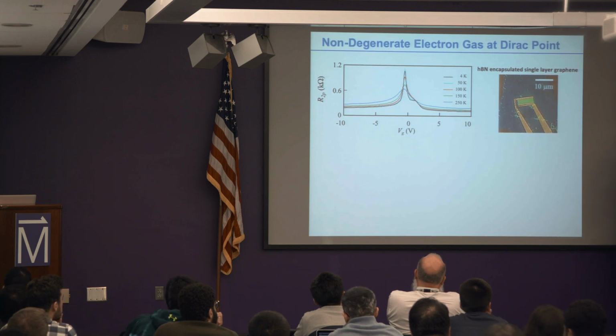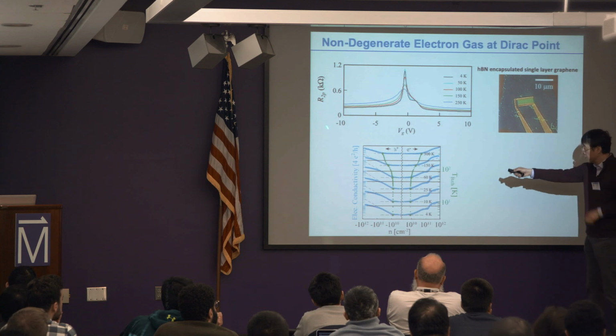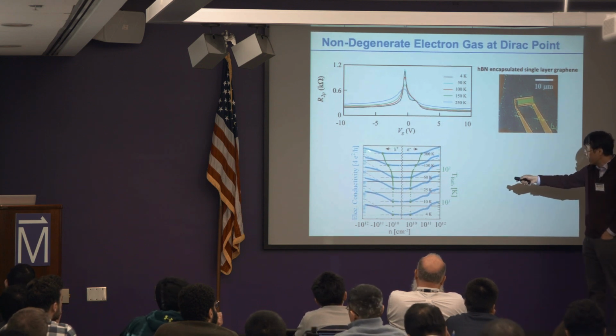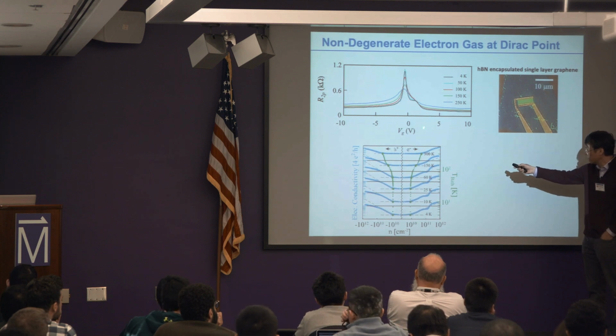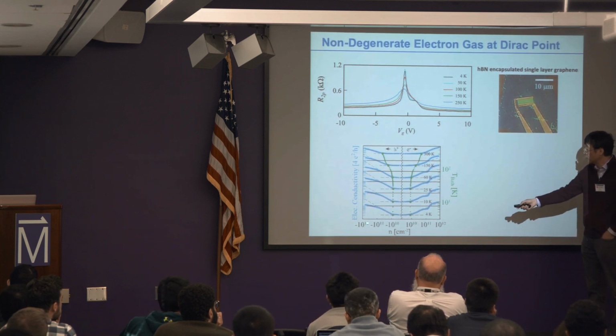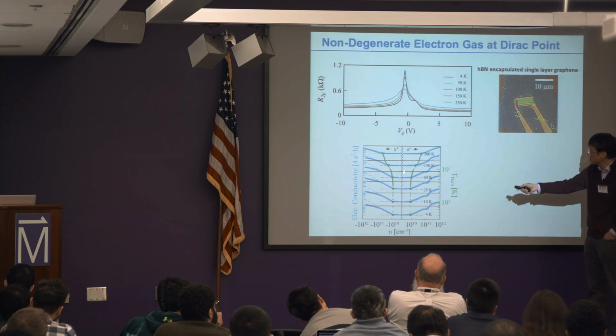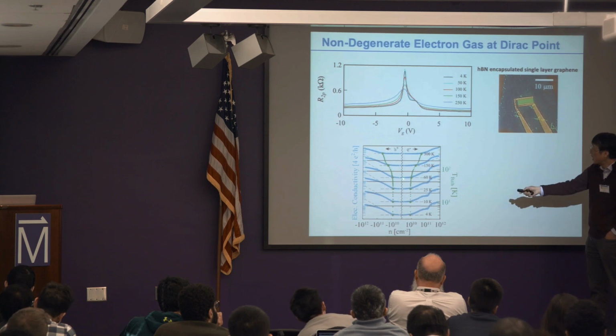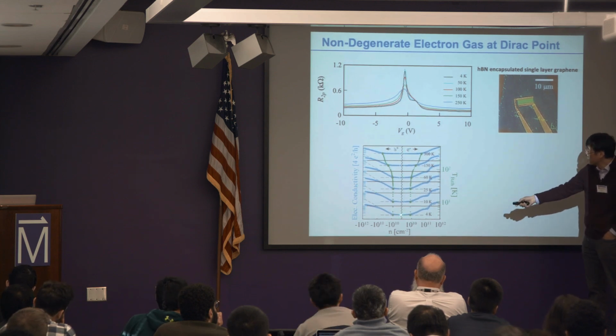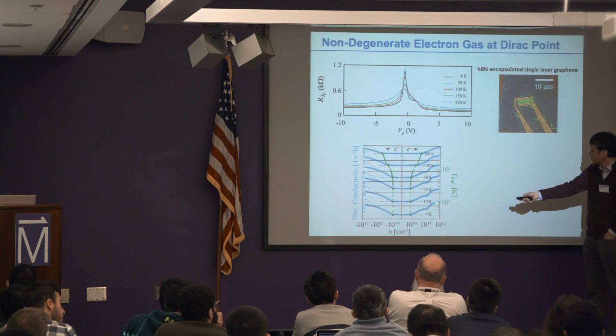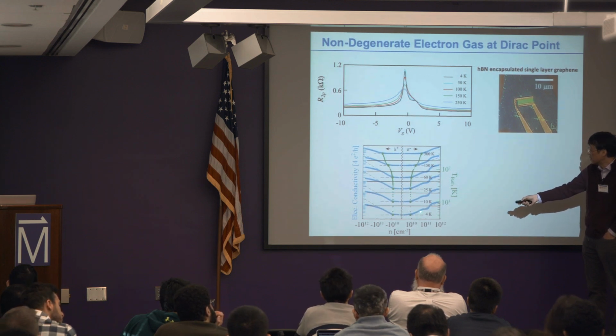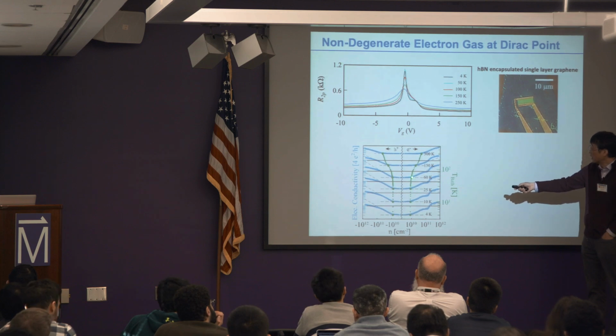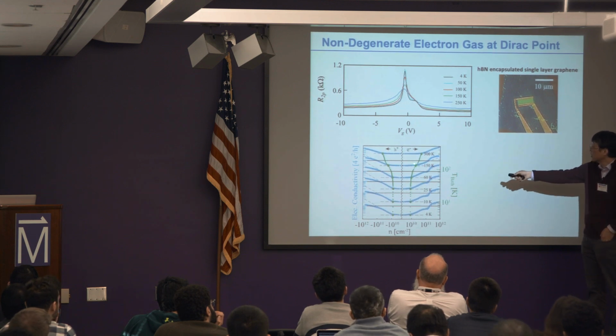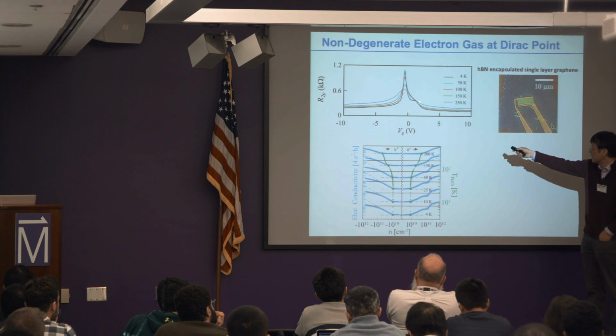A better way to describe this is to plot it again in terms of the inverse, the two-terminal conductance. Instead of gate voltage, I convert to charge density, and note that I put the density on a log scale, with neutrality here. Starting from low temperature, the conductance stays roughly constant at extremely low density, then starts to increase as you go to higher density. That is expected. Now we change the temperature, and this constant range becomes larger and larger. In other words, the peak becomes broader.